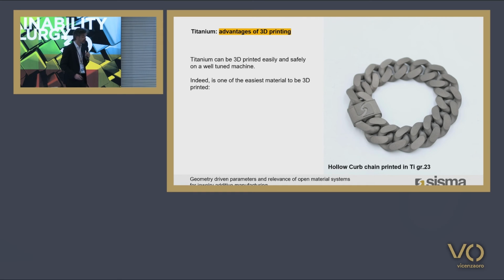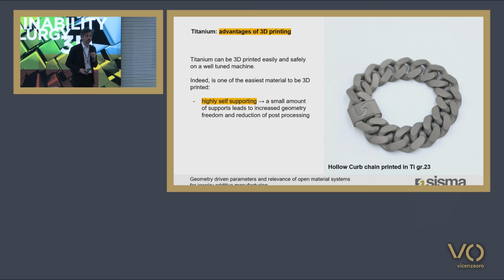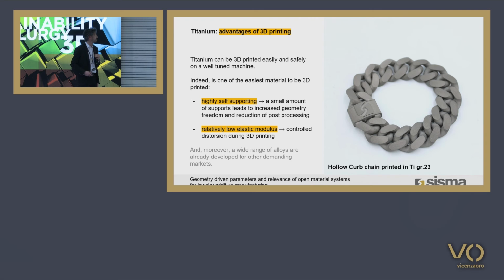As we saw today from a presentation before, casting titanium as well is a very difficult task. And why titanium for 3D printing? Well, titanium is not only an interesting material, it's one of the materials that can be printed more easily. Probably the easiest material to print, for different reasons. It's highly self-supporting. It needs only a small amount of supports, which leads to a small amount of post-processing. It has a relatively low elastic modulus, so the distortion during the process is limited.